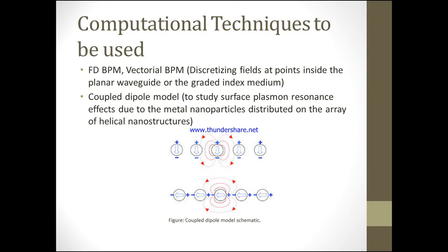The BPM will give us the electric field at the sites of the nanoparticles, at the lattice points which contain the nanoparticles. And then, after we have got the incident electric field on the nanoparticle, we can easily calculate extinction, scattering, and in fact the dipole moments of individual nanoparticles using the coupled dipole model.